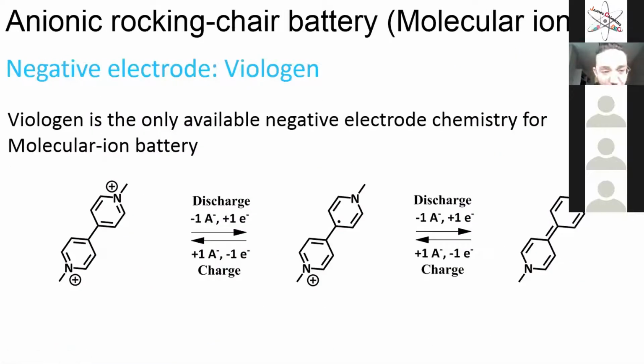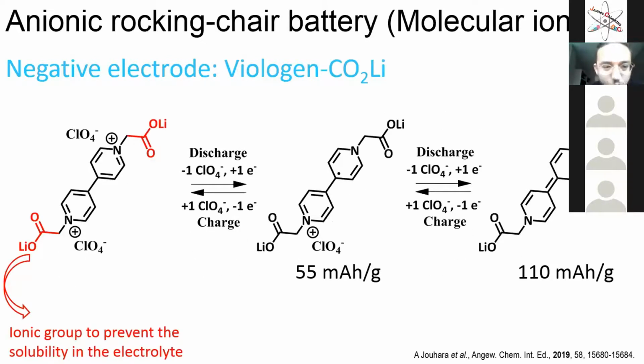For the negative electrode, as I said, viologens are the only available negative electrode chemistry for this battery configuration, and this is how it works. You start with the molecule that is positively charged. You have an anion for charge compensation. So you start with a discharge, you remove the anion, then another discharge to remove the second anion, and you end up with this neutral molecule. But if you use it as such, this one will be soluble in the electrolyte, and then you will lose cycling stability. So if you want to make it stable, it's the same thing. We will add an ionic group, which are the carboxylates.